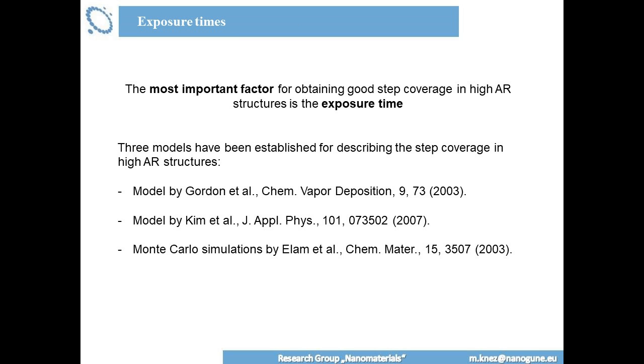And further means you need to think about how long time you need to give your precursors to diffuse. And now we are back again to the diffusion phenomenon, to diffuse into pores. So imagine you have a big pore and you have some gas molecules and they are just diffusing around. They need to enter the pore and then they need to get into the depth of the pore. And this requires time. This requires time for the process scale.